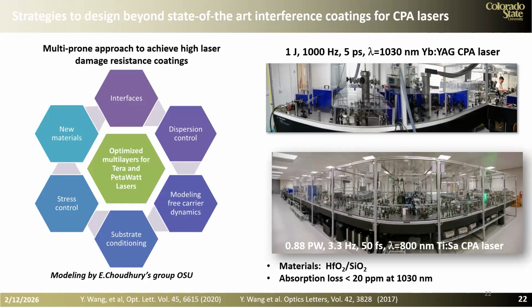So we are going to design coatings for ultra high intensity lasers. And I show here an example of the two lasers that we have at CSU. We have a high repetition rate joule laser that produces joule level pulses. And then we have the Aleph laser that produces petawatt peak intensities at rep rates of up to 3 hertz. So the parameter space is very different. As a result, we need to look for strategies that include looking at new materials, looking at stress control, understanding the role of interfaces, and controlling dispersion.